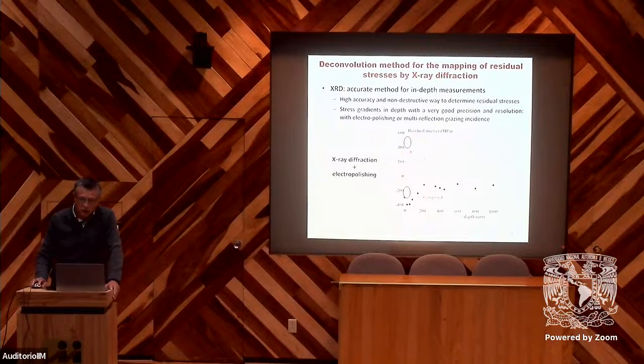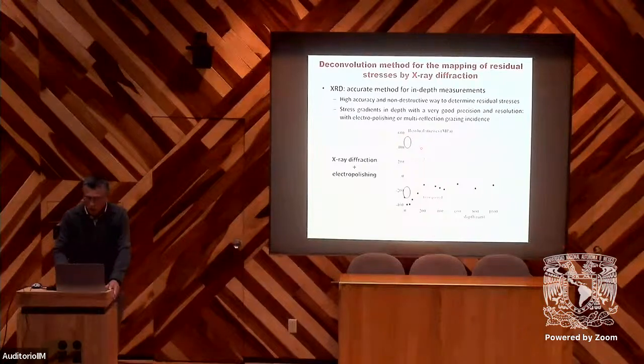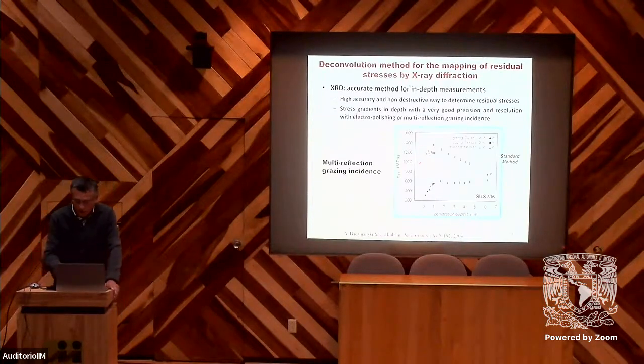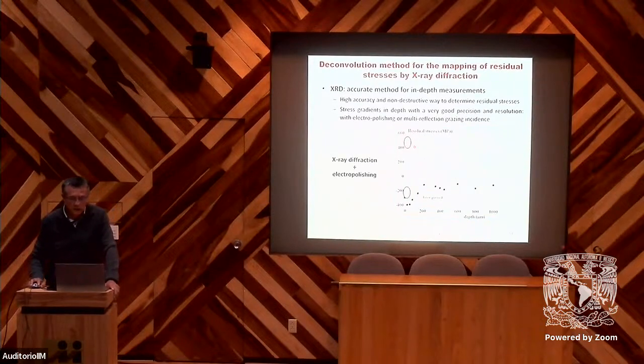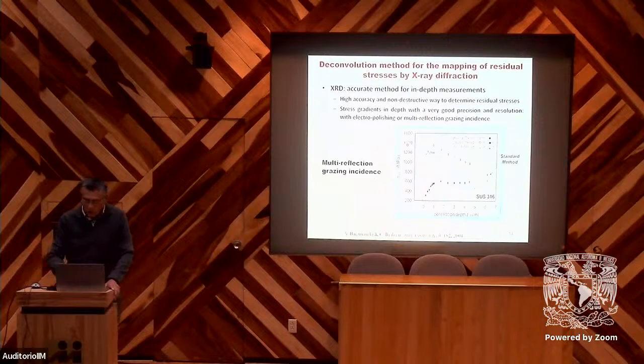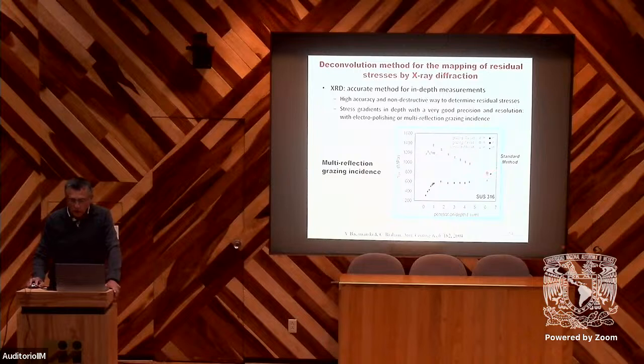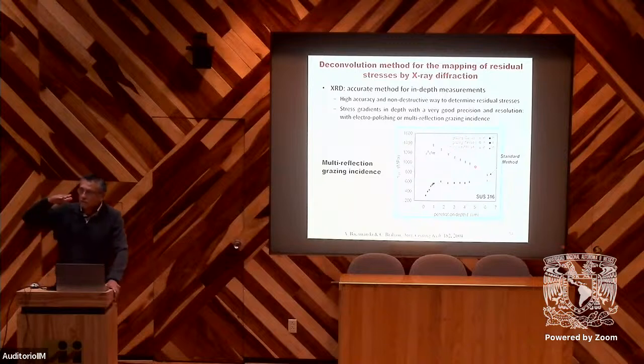And the question is, can we have better spatial resolution? We improve this by using grazing incidence. For this, we measure in the very outer layer, in this part, using multi-reflection grazing incidence. We can compare here what we measured by this technique to the standard method. So we have the possibility to have a very good spatial resolution to measure in depth.